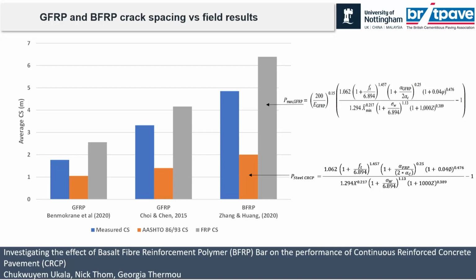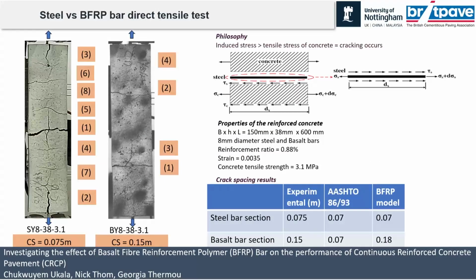Okay, so while the data is not quite enough, because what we are working on is to develop models that represent this as closely as possible, it gives us an idea that we should expect that between the model of the steel and that of this equation, our basalt behavior should be somewhere in between. And so we decided to carry out a little test to show if this was possible or tenable, and we decided to conduct a direct tensile test on 2 concrete prisms, and all we did was just put a bar in between the 2 concrete, 1 basalt, 1 steel,